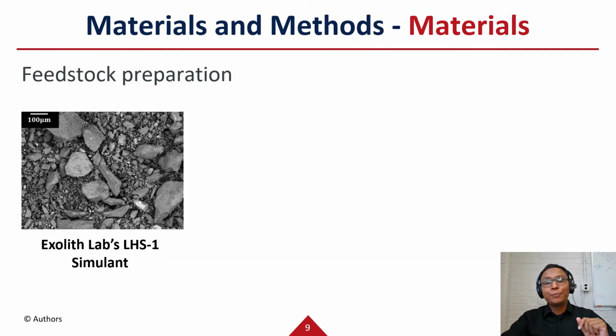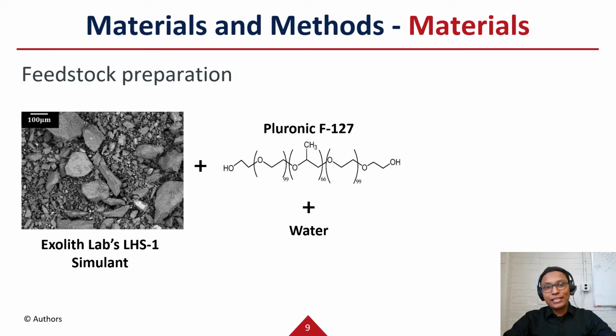Now, I am going to briefly describe the feedstock preparation and the printing setup. It's worth mentioning that because of the limited availability of lunar regolith on Earth, current research findings are based on simulants of the actual lunar regolith that are commercially available. We used the lunar highland simulant from the Exolith Lab at the University of Central Florida. The as-received simulant was used with minimal pre-processing for the AM process.